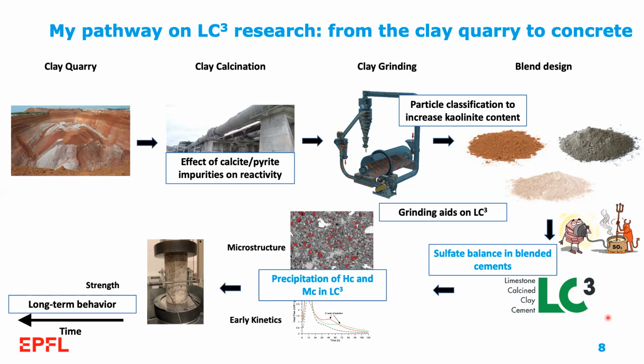aids, particularly alkanolamines on LC3, in order to improve the grinding process and also develop strength over time by interaction with the aluminate phases. The sulfate balance of blended cements, and particularly LC3, is something that I study in detail and that I will talk about in depth during this presentation.